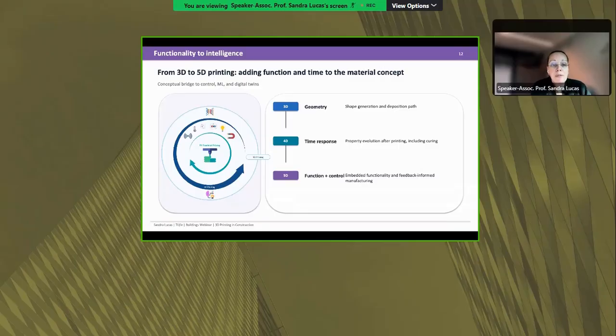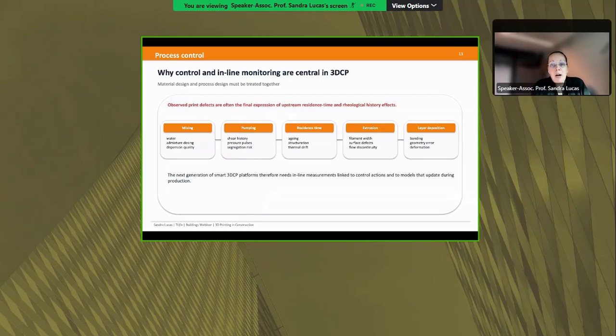So then we move to what I call the 5D printing. So trying to embed the functionality, but also the control. So the function plus the control in the system. And we took the step to improve how we control our printing process. And in that line, our printing systems are now already capable of reading in line some properties of the material. So we can, for example, read the pressure, we have temperature, we have flowability, we can also read the water content, but we still have a lot that we need to develop and improve in this inline sensor measurement. The goal here is that we develop inline measurements that can help us control the material in real time, because that's what we notice that we still lack in the system.